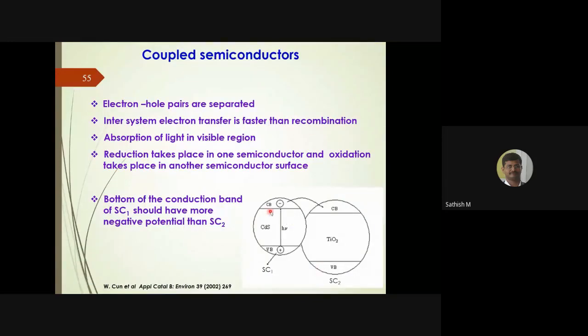As I told you, one of the advantages, for example, is that TiO2 is active only in the UV region. Instead of that, you can couple it with another chemical, preferably maybe cadmium sulfide. In such a case, cadmium sulfide will absorb the visible light, and then the electron may be transferred to the conduction band of TiO2. So the reduction reaction takes place.